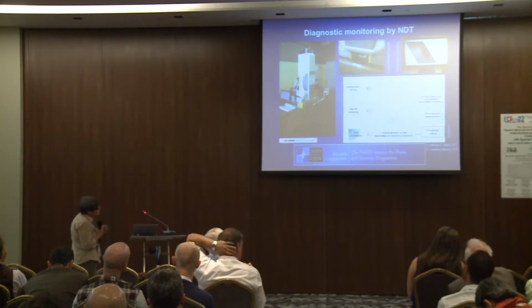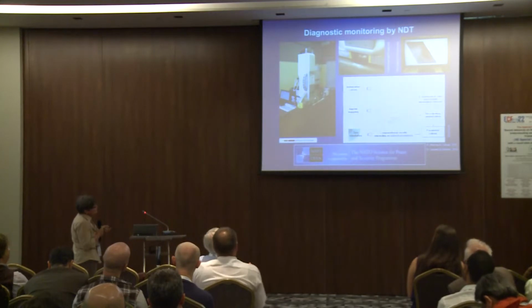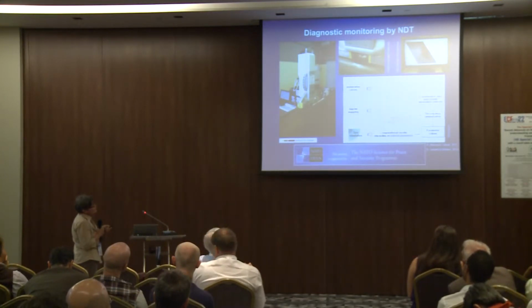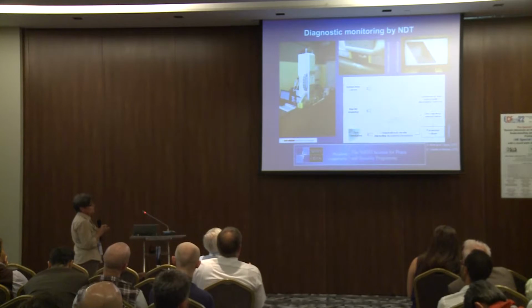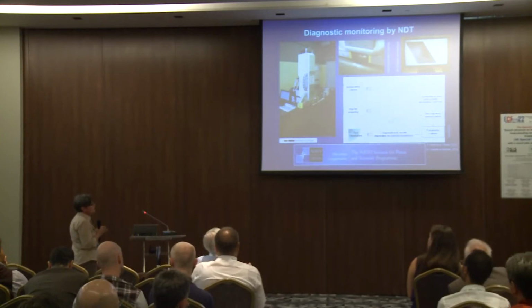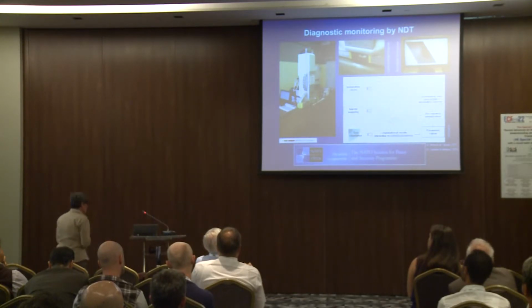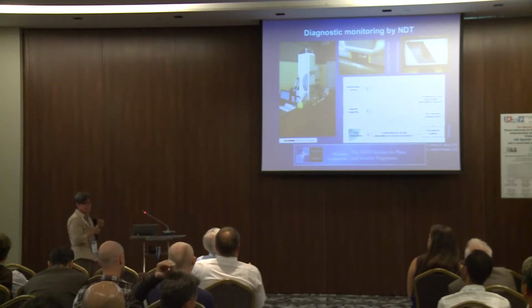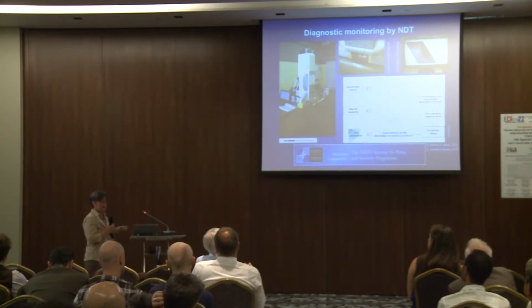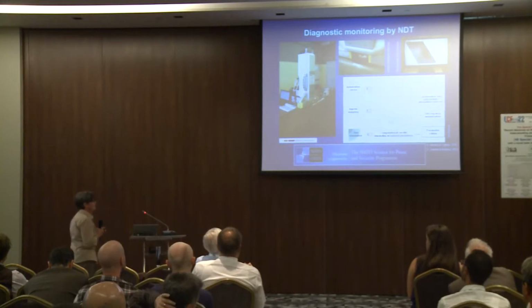And with a small tool like this one, possibly you can also detect the full geometry of the imprint which is left on the material surface. And the former study has shown that if we couple this experimental output with a suitable simulation of this test, then we can infer the material parameters with higher accuracy and reliability.